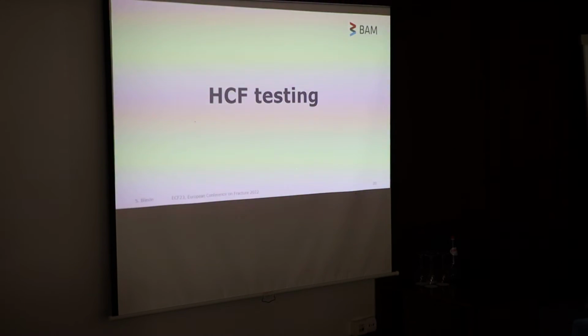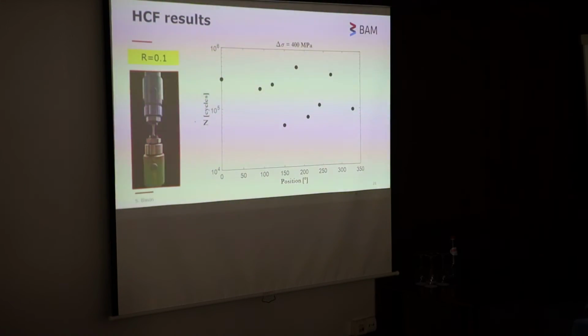And according to the high cycle fatigue testing, we only have collected specimens from the upper part of the cylindrical part of the vessel. When we compare the number of cycles for different positions, here we are always using the same stress range, because we are not able to define the S-N field, and also because we want to identify some kind of differences in terms of behavior comparing different positions.